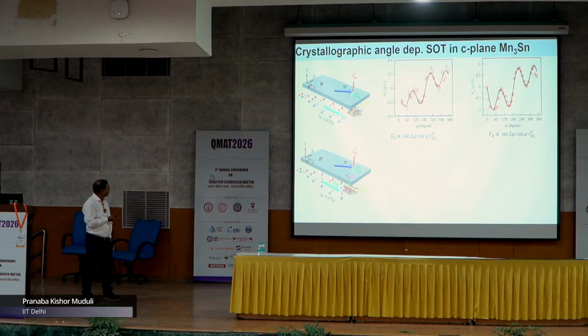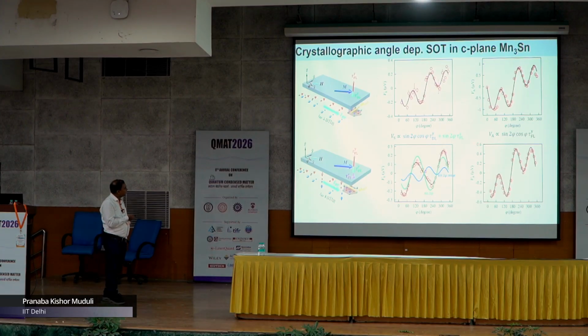But now if you apply the current along the octupole moment, you have to make a device where the current is in a different direction, and then we see this additional component which cannot be explained simply. You need the sin 2φ dependence, which is a signature of the out-of-plane spin current being generated.